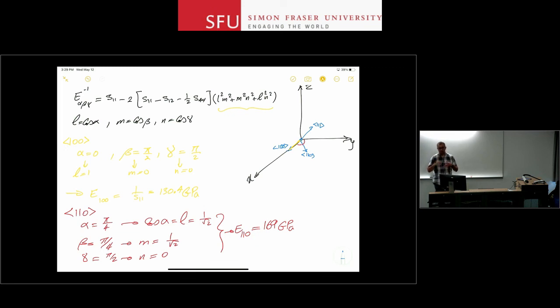If you have situations where you have, for example, curved beams or spiral structures or things like that, you can come up with an approximate solution using some value in between, let's say 130 to 170 gigapascals, and leave the exact solutions, if they matter to you, to simulations. So that's that for our discussion on the mechanical response of materials.